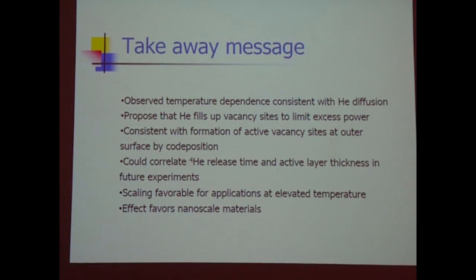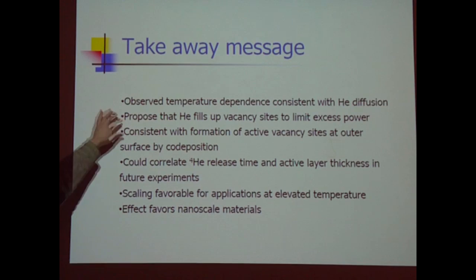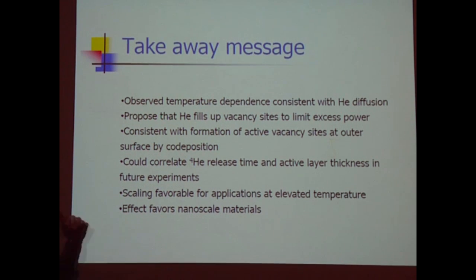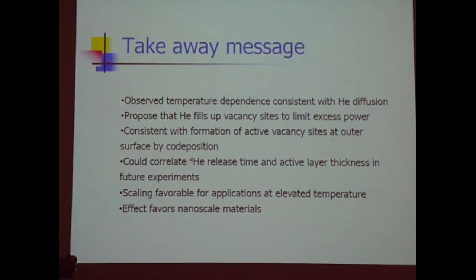Observed temperature dependence in these experiments seems to be consistent with helium diffusion. I propose that helium fills up vacancy sites and provides an upper limit for excess heat production, a mechanism for limiting excess heat production. This is consistent with the picture we've been building up of formation of vacancies by co-deposition on the outer surface.